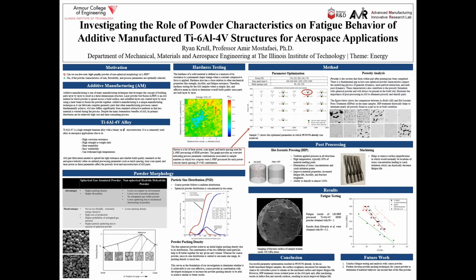Another drawback for fine powder is, since it is smaller in size per particle, what occurs during the build process is something that is called spattering due to the ejection of these smaller particles. But how about coarser powder, which isn't spherical? So unlike fine powder, its production costs are significantly lower, thus more eco-friendly. It requires less energy to produce. Also, there is low spattering that occurs due to the varying geometry and the larger size of these particles compared to the fine ones. The catch, though, is coarse powder having a lower packing density, which leads to a significant portion of my research moving forward, which is developing techniques to increase the packing density of coarse powder.